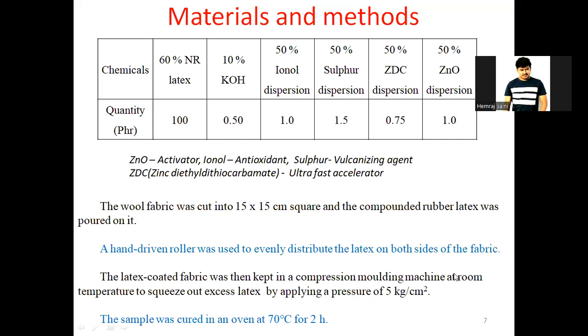I used a hand-driven roller for making a uniform dispersion for coating. The coating was done on both sides, and after coating, it was kept under a compression molding just to squeeze out excess latex. We have not given any pressure or temperature. This is not a curing process, only to remove the excess latex. So this is the process.